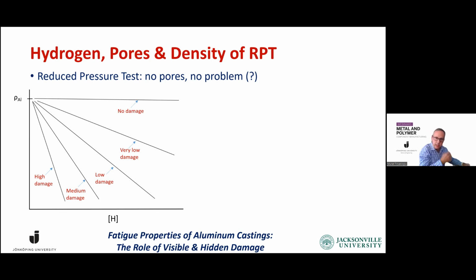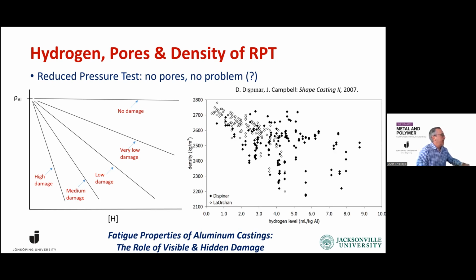In the manage the damage presentation, I outlined, and I even gave examples from the literature of how much supersaturation of hydrogen is reported. It was 313 times above the solubility. Okay, so when we look at the data, for instance, we can immediately see that this is reflected in the data, the effect of the damage. So what we do by degassing is, if we have this kind of sensitivity to the hydrogen level, by bringing it down, we basically shut it off.